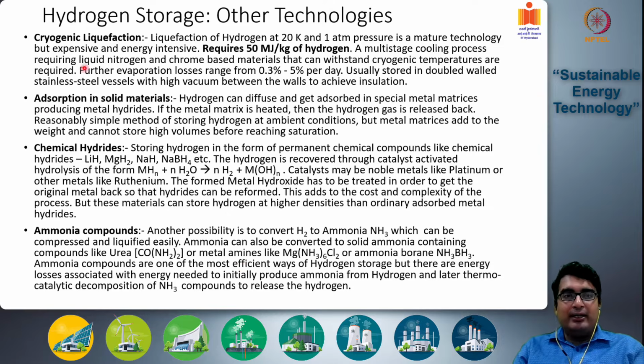A very mature technology is cryogenic liquefaction, which we discussed earlier. You are basically cooling the hydrogen to the point where it becomes a liquid instead of gas. The problem is you have to cool it to around 20 kelvins, or at least below 33 kelvins if you are looking at high pressure systems. But if you are looking at a 1 atmosphere case, then you are looking at 20 kelvins, okay, which is an extremely low temperature. While the technology is mature because it was developed to create liquid hydrogen for rocket propulsion in space technologies, it is quite expensive and energy intensive.